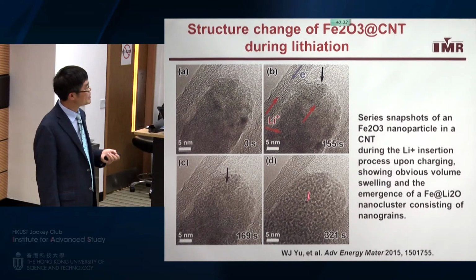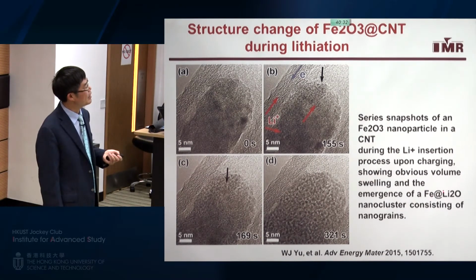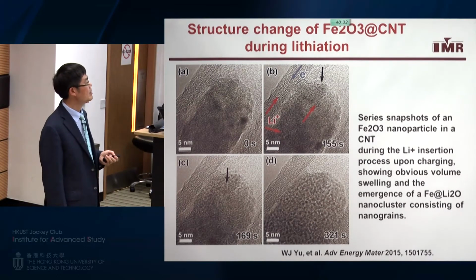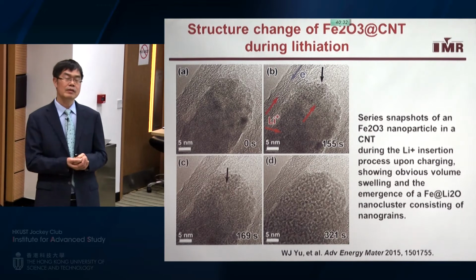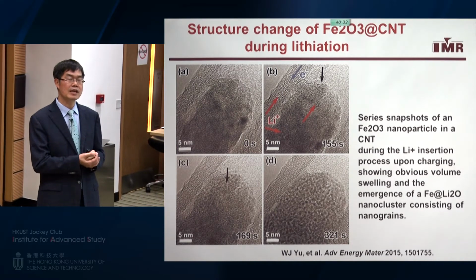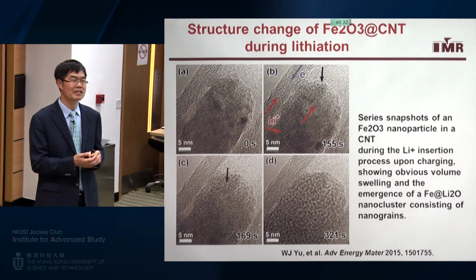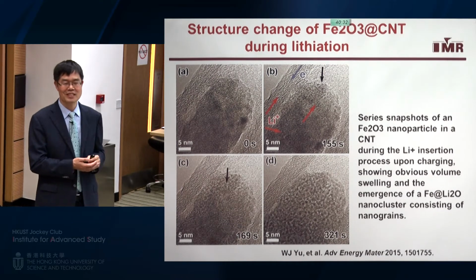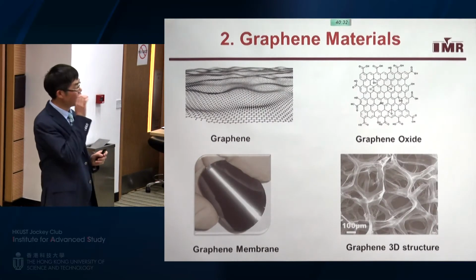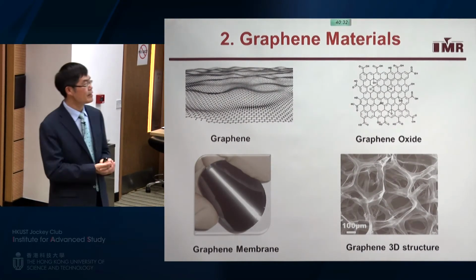We can investigate the structure change during charging. For example, after lithiation, we found that we can form this kind of structure, lithium oxide with iron nanocluster, inside the nanotubes. So this is quite a good way to investigate the mechanism of formation and deformation of electrode materials in situ in carbon nanotubes. But it is very difficult to do this kind of experiment. Okay, so I will move to the second part.